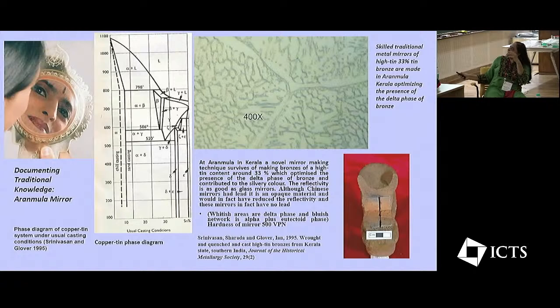So where the genius comes in is that they try to use a very skilled technique to cast this delta bronze in a way that minimizes the brittleness and maximizes the presence of the delta phase. And then because it's a very hard compound of about 500 VPN, it can take a very good polish to give a metal mirror finish.